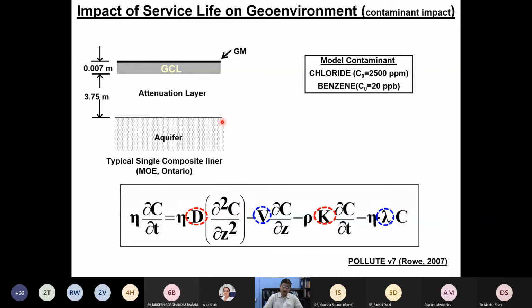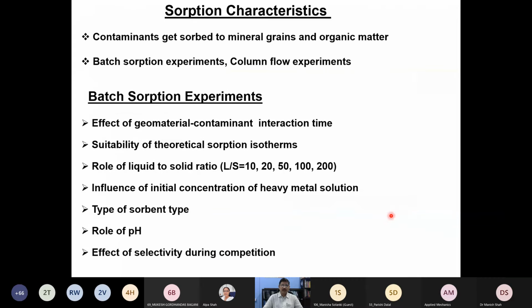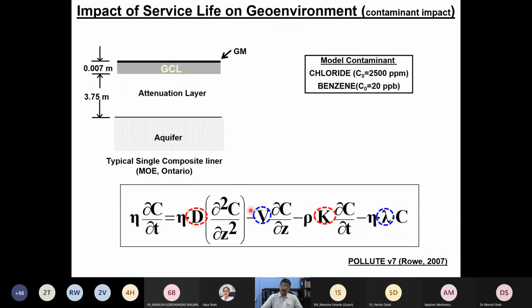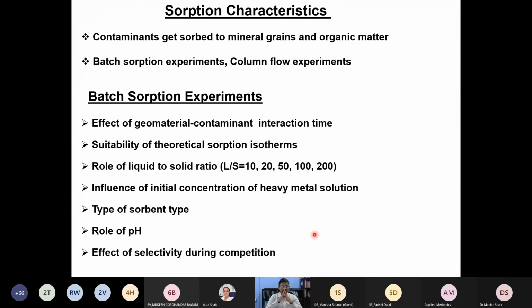these parameters. One is how to measure the diffusion coefficient, how to measure the advective velocity, and how to measure the partition coefficient. In the case of a landfill, we may have to worry about it only in the case of benzene, but in the case of chloride, this becomes zero. This term will go off. So let us try to look at this one. The first term I'm really aiming at is K, the distribution coefficient or the partition coefficient. We commonly perform two varieties of tests.